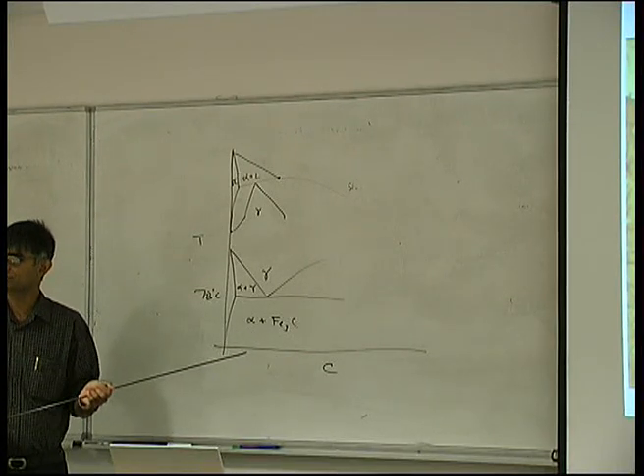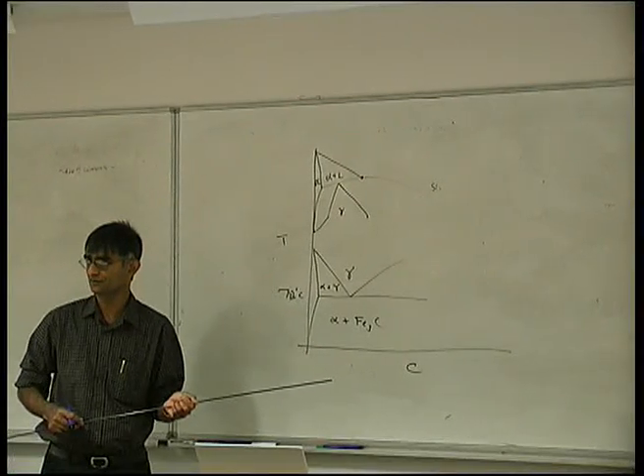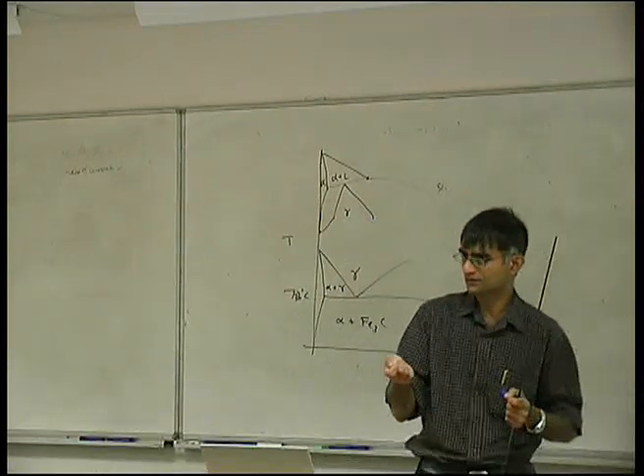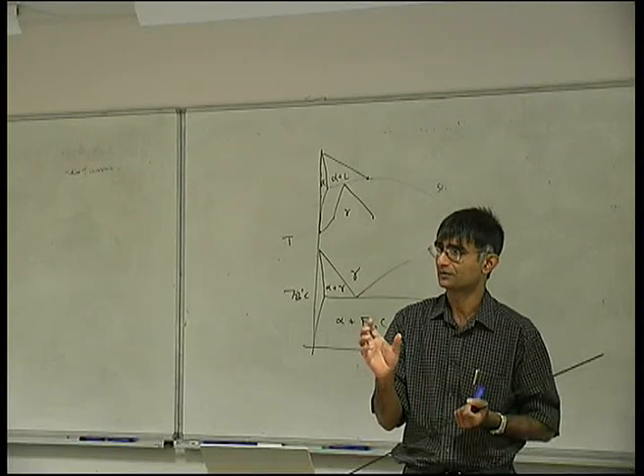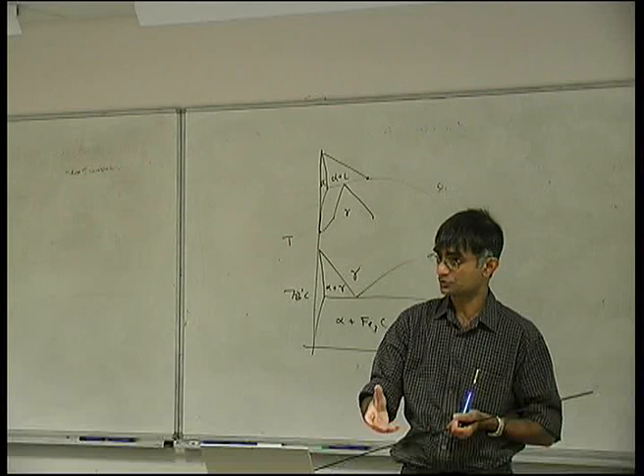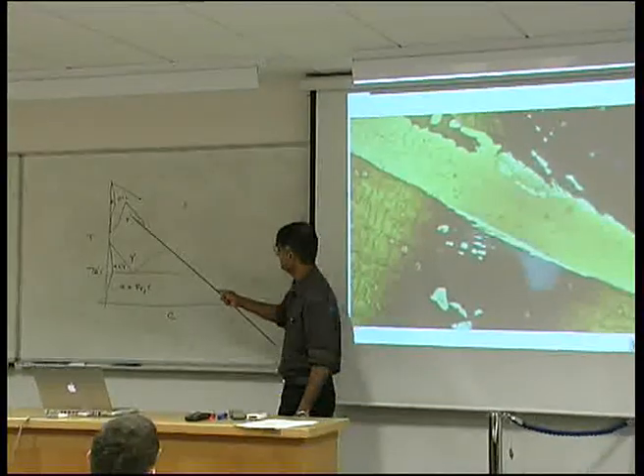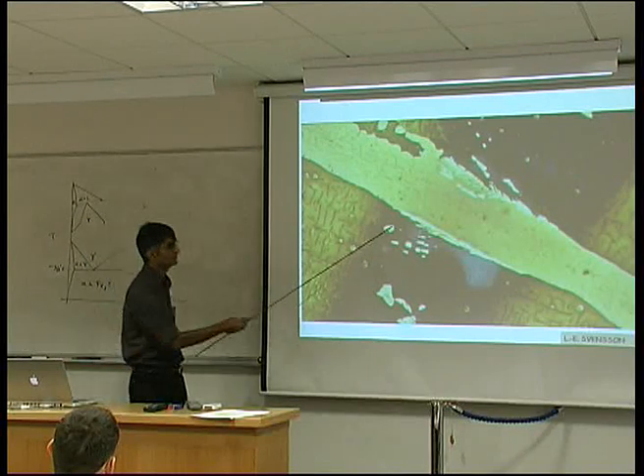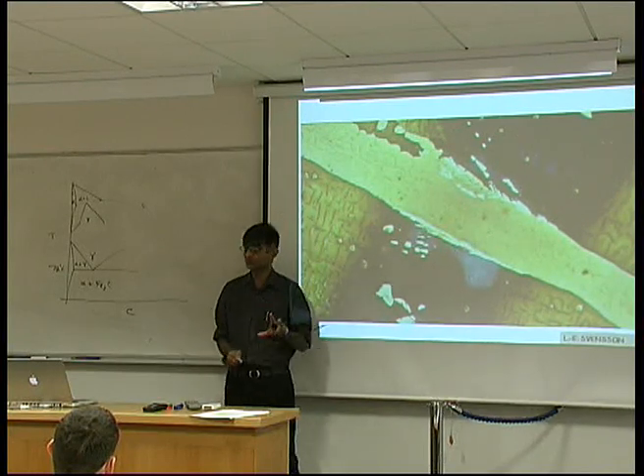Not only is the ferrite magnetic, but austenite itself has magnetic properties — very subtle but extremely important. Normally you can't attract austenite with a magnet; austenitic stainless steel won't be attracted. But we can make austenite ferromagnetic. At very high temperatures there is a Curie temperature, and at extremely low temperature there's a Néel temperature corresponding to an antiferromagnetic transition. The first grains to solidify, when carbon concentration is below the peritectic point, are grains of delta ferrite. Austenite nucleates at the surfaces of those grains and completely consumes the delta, leaving columnar grains of austenite.